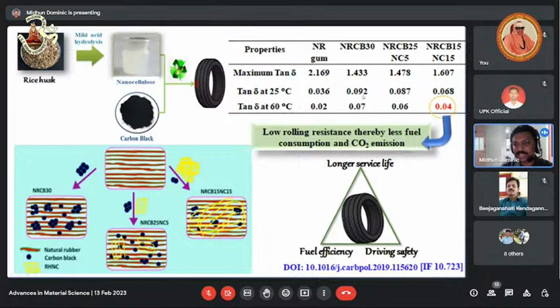NRCB30 tan delta at 60 degrees Celsius is 0.07. In NRCB15, NC15 means nanocellulose. So if you replace 15 PHR of carbon black with 15 PHR of nanocellulose, tan delta at 60 degrees Celsius can be decreased from 0.07 to 0.04. So we can decrease the rolling resistance by the synchronized use of nanocellulose and carbon black. But the same trend we also obtained here: we have to compromise on other mechanical properties like tensile strength, tear strength, abrasion resistance index, and so on.